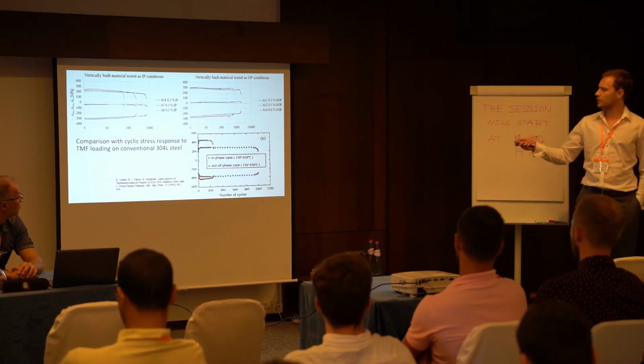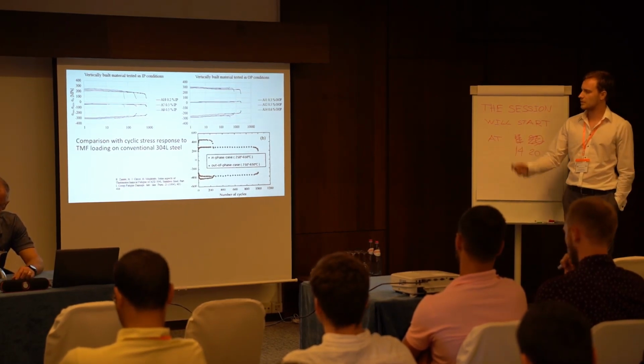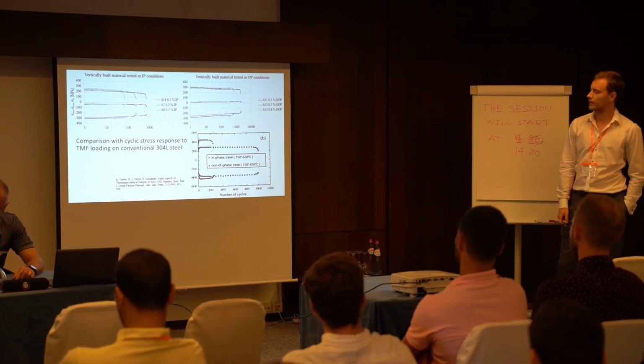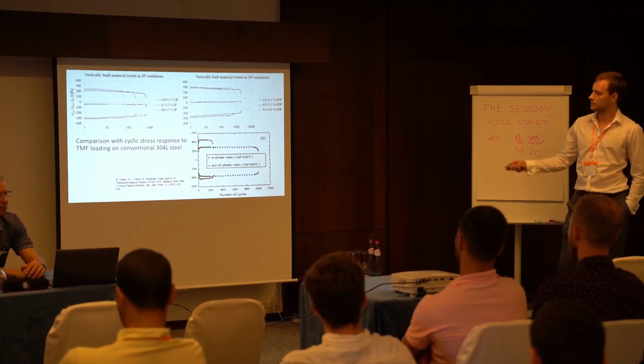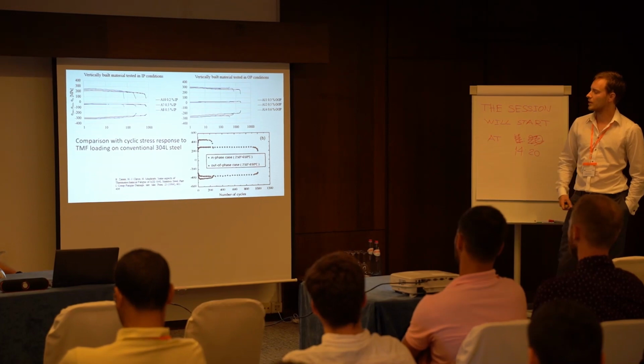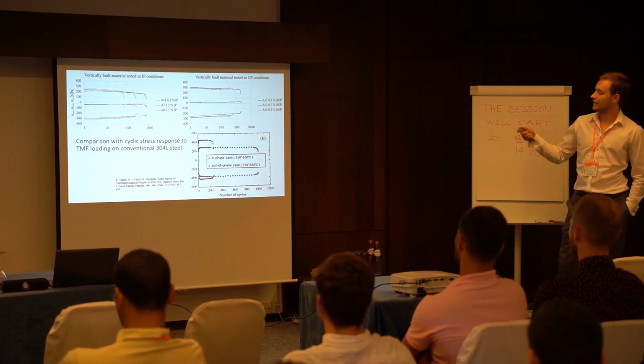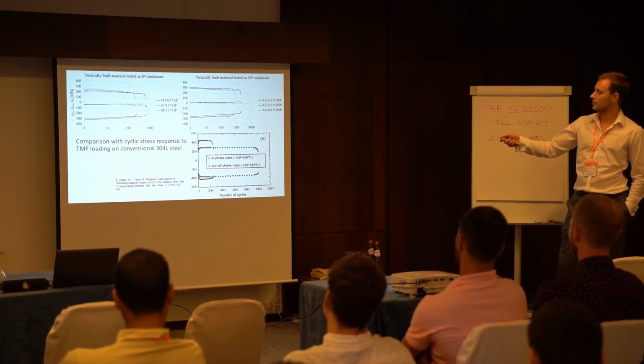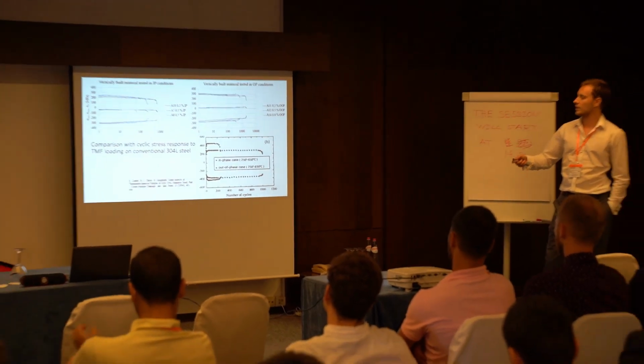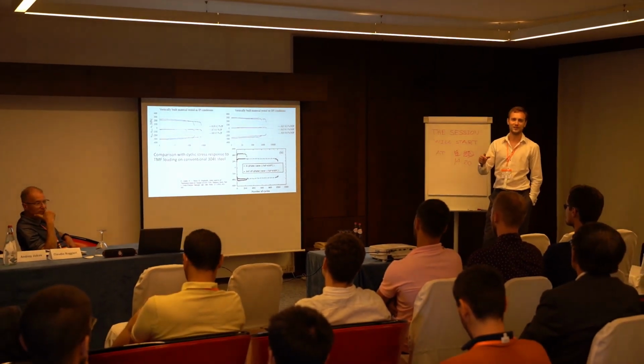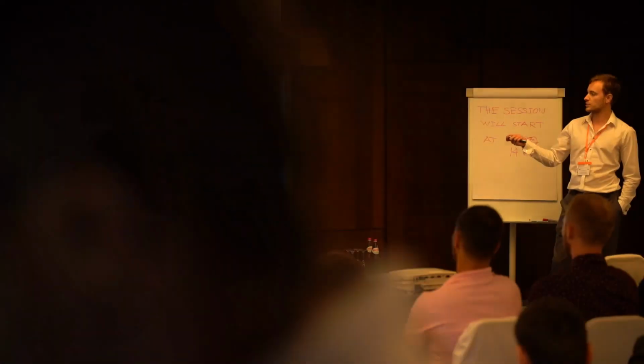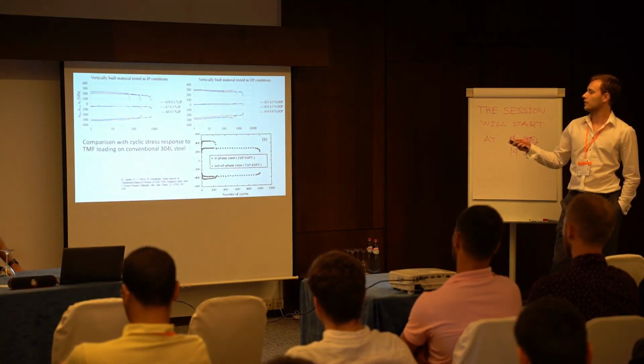Yeah, so if we compare it with the conventional material, in this case 304L steel, which was subjected to a somewhat similar temperature range, we see that in the case of conventional material, the initial hardening period is also short, but not so short, let's say. I'll later explain why. And also the stress response was after that saturated, in both in-phase and out-of-phase testing conditions.